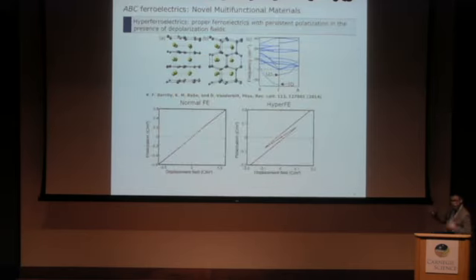But now I'm going to jump to a slightly different topic because these ABC ferroelectrics are, I believe, a very robust platform that can enable many novel functional properties. It was proposed that some ABC ferroelectrics are hyperferroelectrics. I think it's a very interesting property: a proper ferroelectric with persistent polarization in the presence of depolarization field.